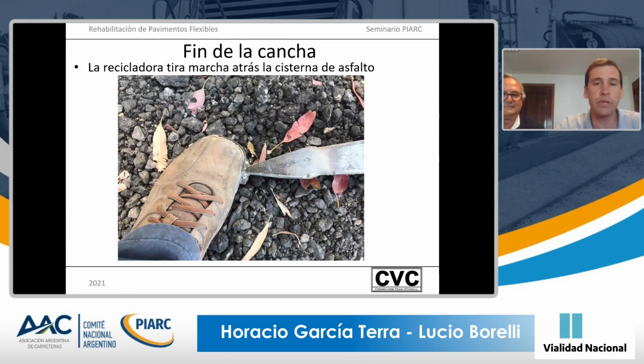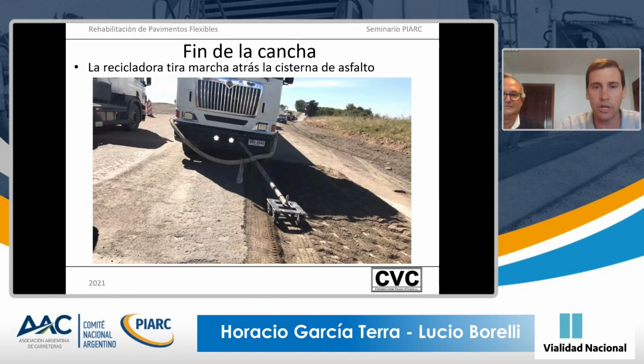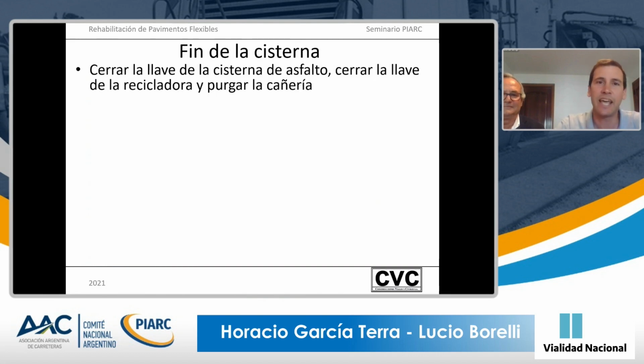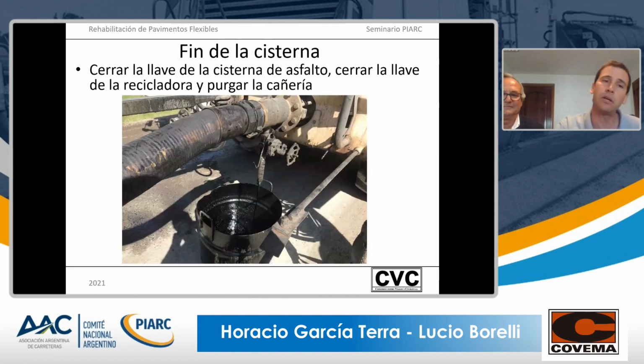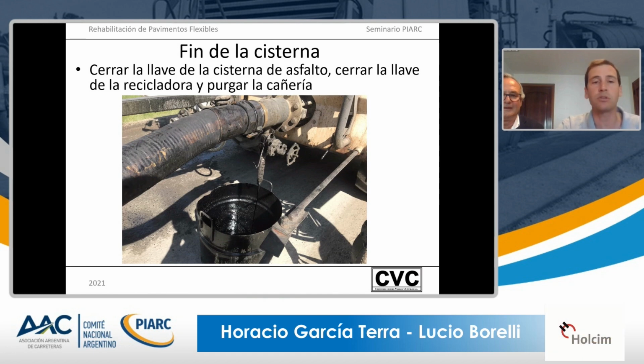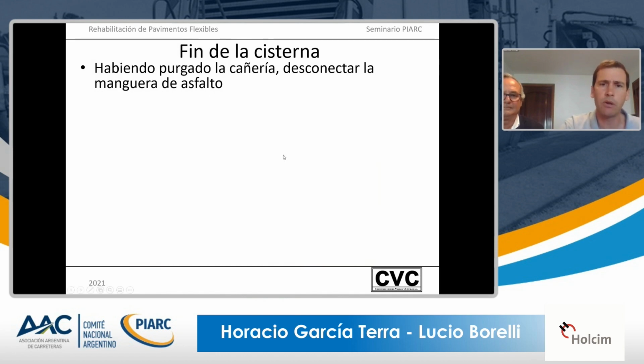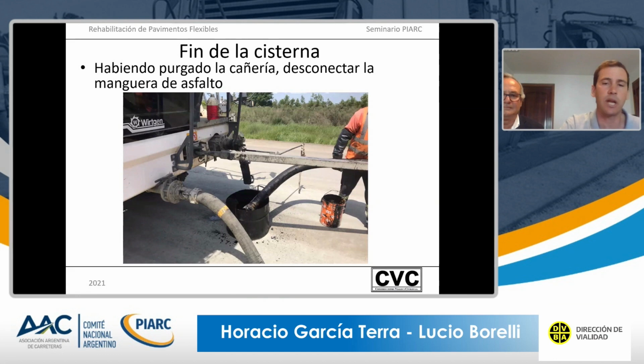5 days later we realized that there were some issues and some things that were missing, and we had to do some things to solve this issue. First of all, we need to close the water tank valve and the asphalt tank valve, and close the recycling valve and purge the pipeline. And those 25-30 liters will be dumped into a 200-liter drum.